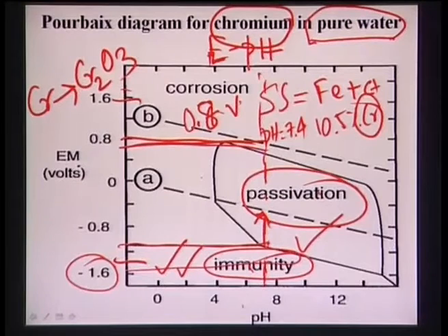So, there the environmental effect, because of the presence of the sodium chloride and all, will be much more significant than in a pure aqueous environment, and again it may be so that your passivity region is reduced or contracted, and therefore, with a simple increase above 0 volt, the material can go to the corrosion region. Okay. So, in that kind of SBF environment or in vivo environment, this particular diagram will not be valid anymore, and you need to construct a separate diagram by conducting tests in the simulated body fluid, the solution which will simulate very closely the in vivo environment.